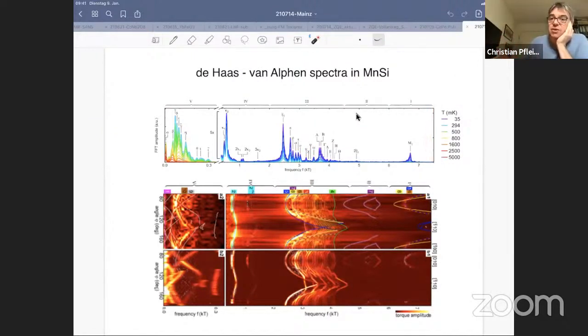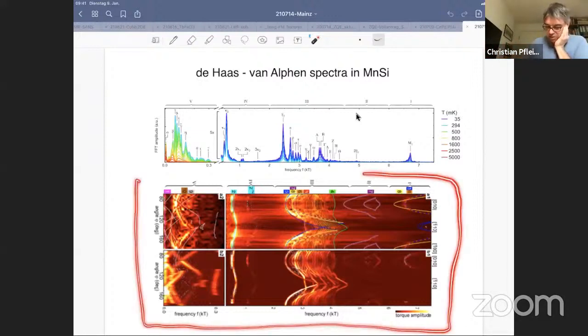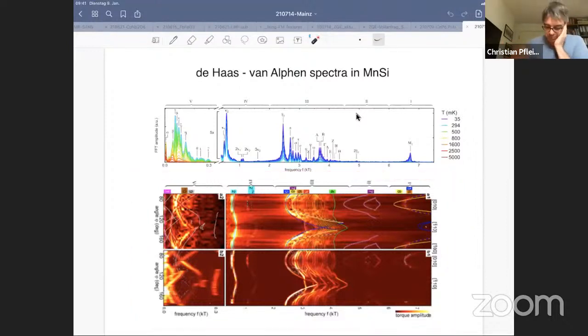And if you change the orientation of the field, you can map out the frequencies. This is a rotated plot, and again, I apologize for the poor quality, as I said, last minute before I started the presentation. You can see that some of them are highly dispersive, some are not dispersive. And now this is really a very, very difficult job to do the proper assignment, and all of this you can find in this paper that was just recently published. So I'm not going to go into the details there. There are a few frequencies which are the really interesting ones.